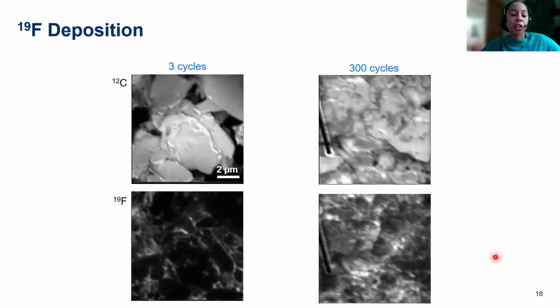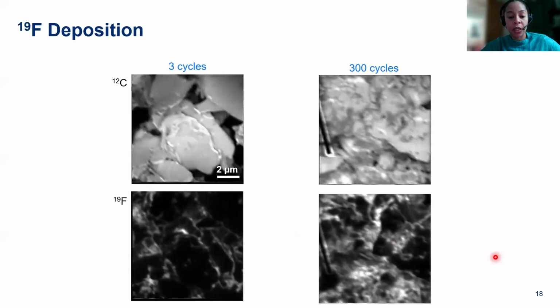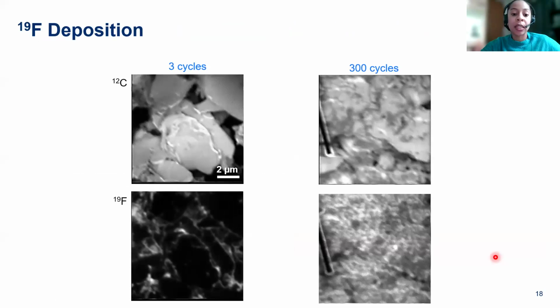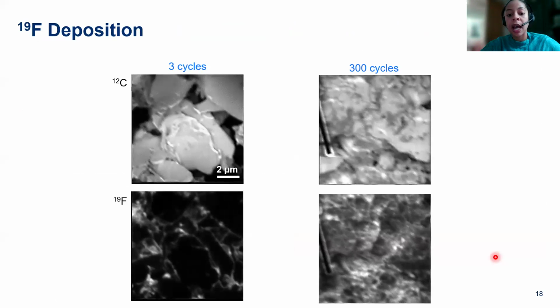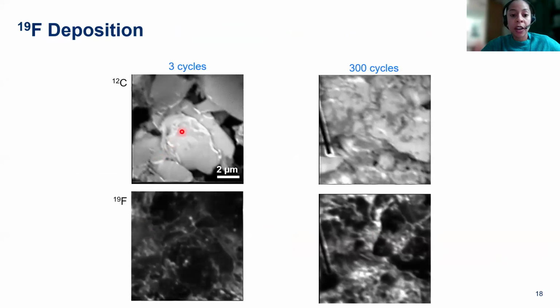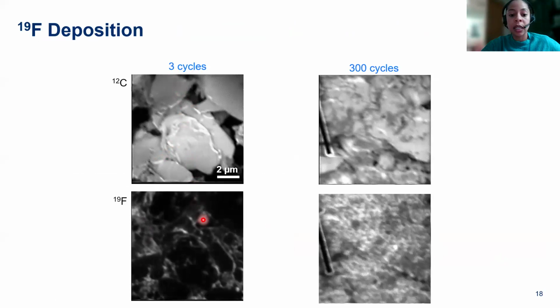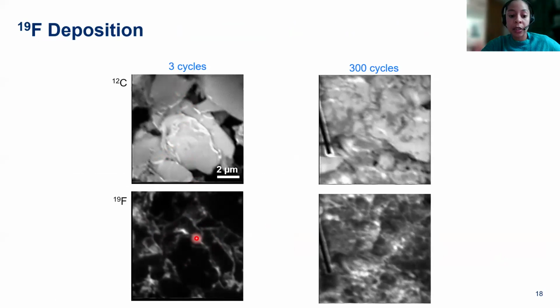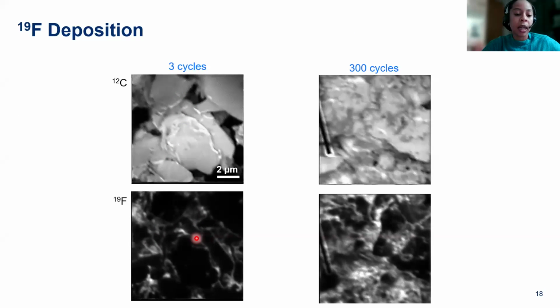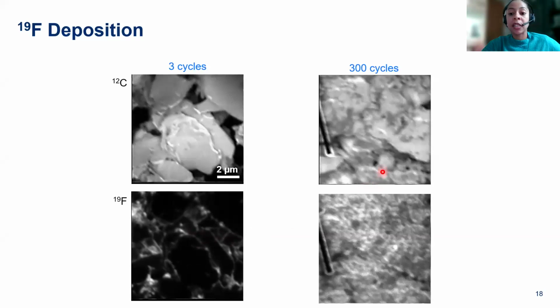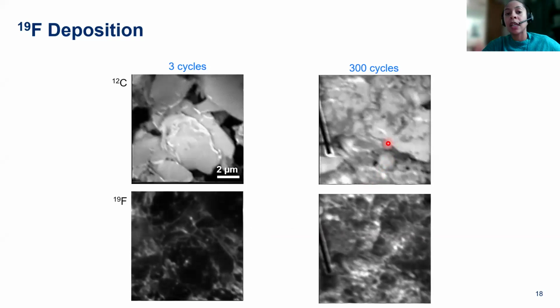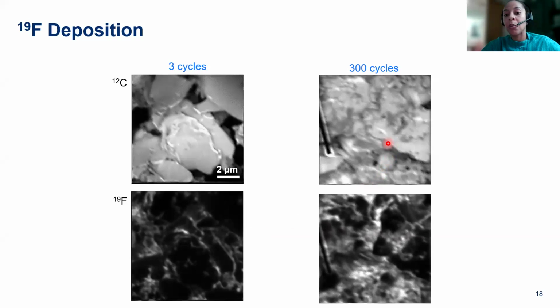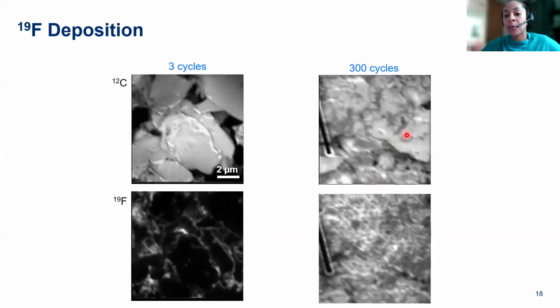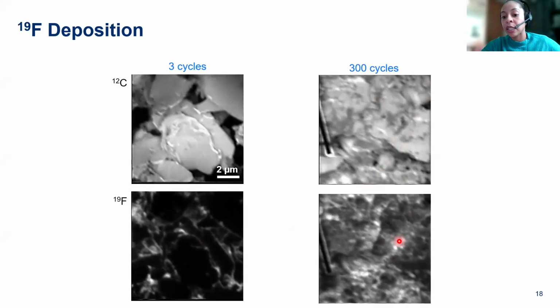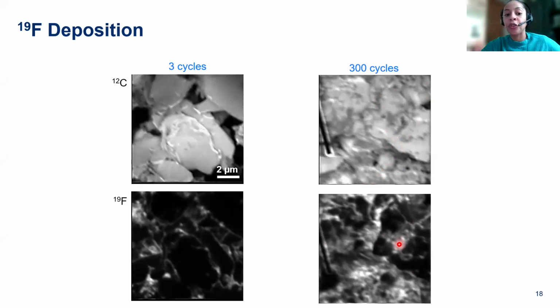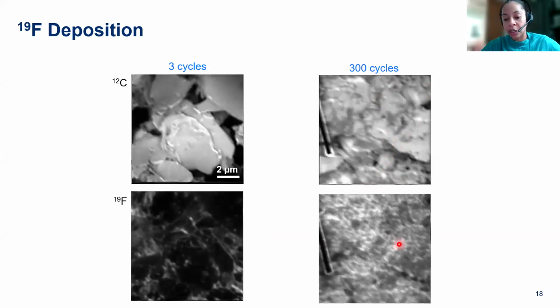Now, because as I mentioned before we can build up successive planes of images, we can create little GIFs that show what the sample looks like from the top surface as we remove successive layers. On the left, we have the short cycle, 3 cycles, and we can see that we have very little fluorine on the surface and it goes away a little bit as we go through successive planes. But this effect becomes much more pronounced when we look at the sample that has been aged for a much longer time. We have a lot of material on the surface, and as we go through the successive planes, we can actually see that we're removing those successive layers of fluorine on the surface.